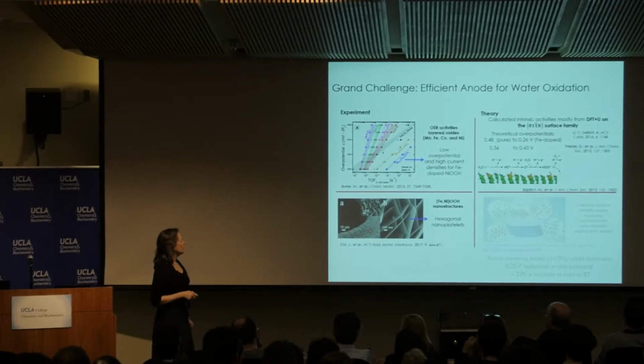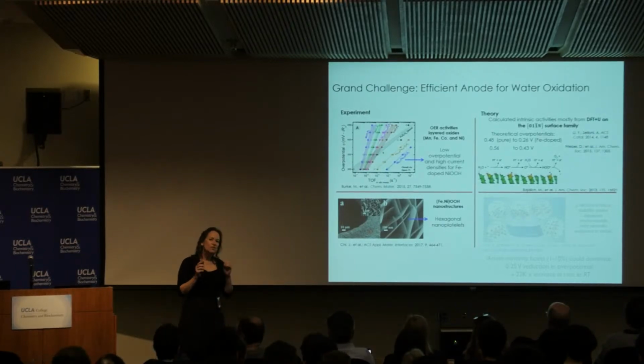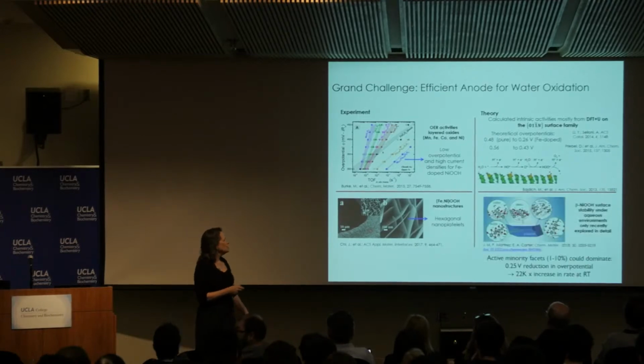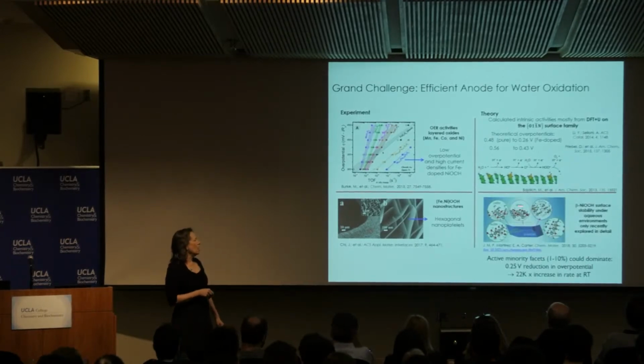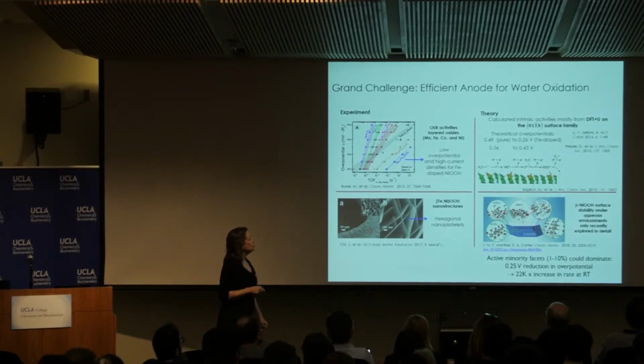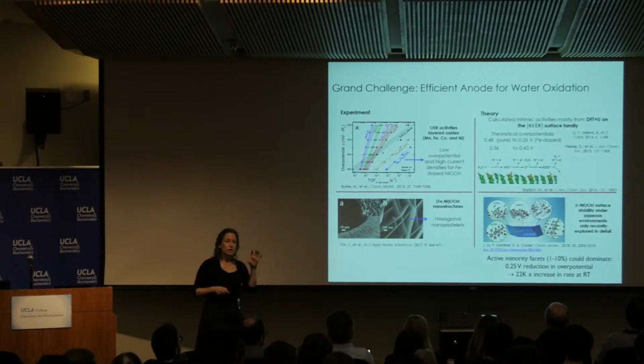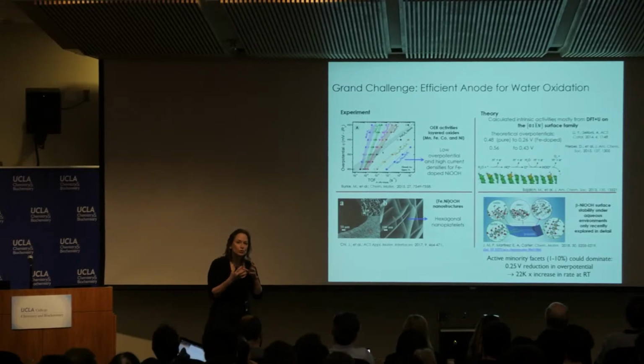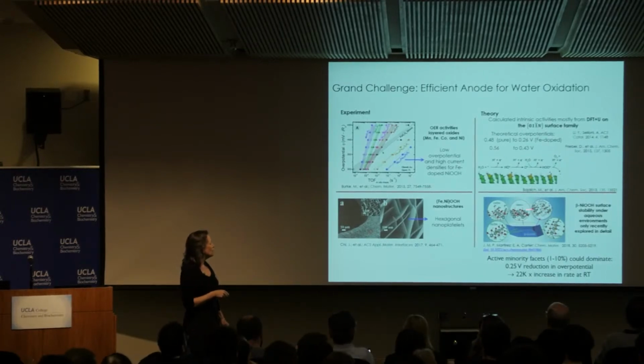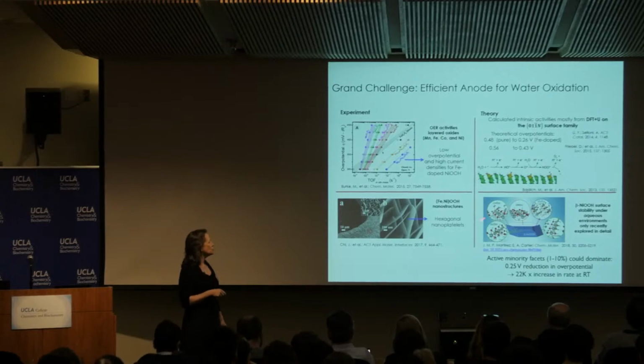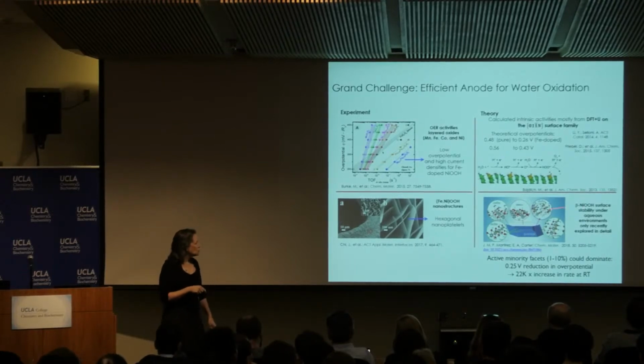And so Mark, who I said was sitting in the audience here, what he did with that information was to do a very rigorous, really the first rigorous study to look at the different facets of this material, the nickel oxyhydroxide, in the presence of water, and to then use the information about the interfacial energies to do what's called a Wulff construction in order to be able to say what the most stable crystallites would look like. And so that work was published now a couple of years ago.